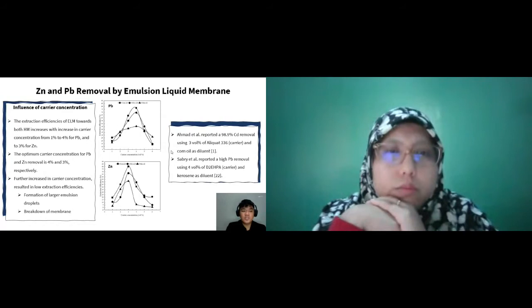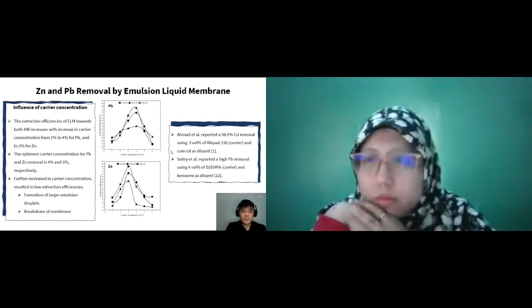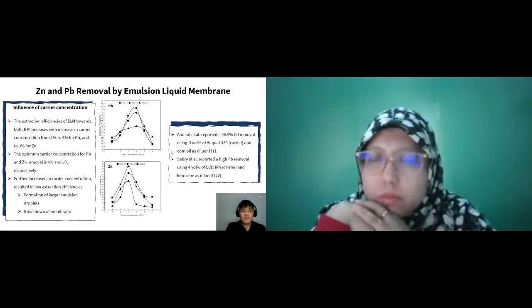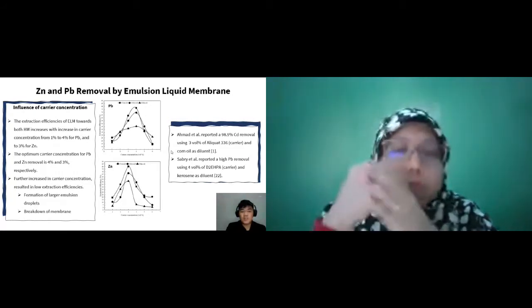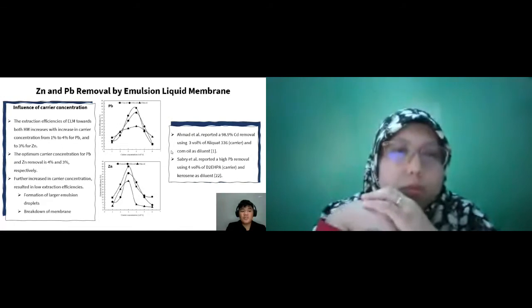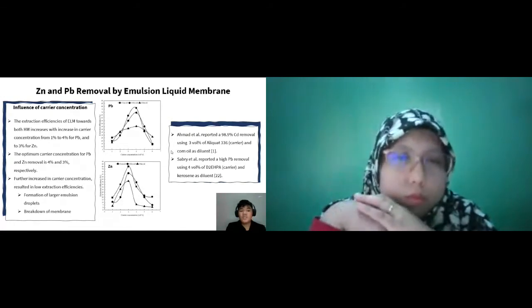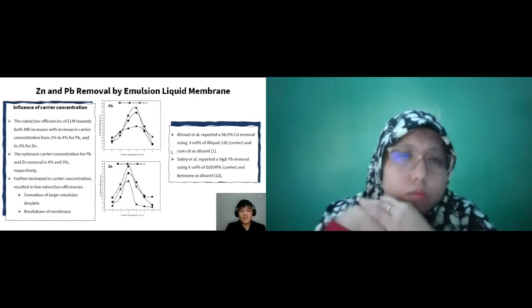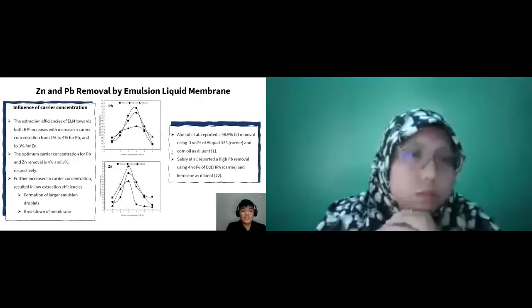Increased carrier concentration also increases the emulsion viscosity, which leads to the swelling of emulsions. So emulsion swelling will dilute the internal phase, and the solute for the heavy metal ion will be released back to the external phase. This will reduce the efficiencies of heavy metal extraction by the emulsion liquid membranes. So comparison with other studies has been made.